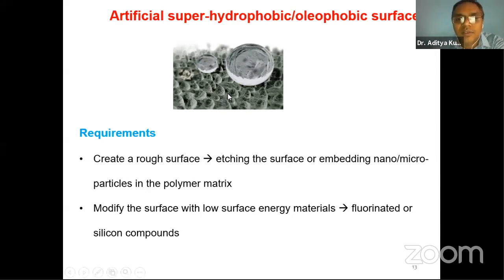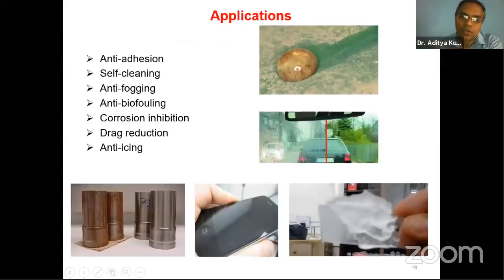Why do we need the roughness? In between this rough surface, you will have trapped air. This air, beneath the water drop, tries to uplift the water drop. So your contact angle will increase if you increase the surface roughness, right? So these super hydrophobic surfaces have lots of applications, like anti-adhesion, self-cleaning, anti-fogging, anti-biofouling, corrosion prevention, drag reduction, and anti-icing. I'll give some examples.